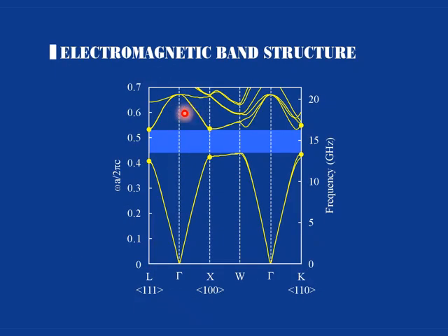So, okay, this figure shows the obtained electromagnetic band structures. This yellow line shows the Maxwell equation answers. Okay, here there are many Maxwell equation answers, and of course at lower frequencies also. So in these areas the Maxwell equation has answers, so the electromagnetic wave is possible to transmit to the opposite side. However, you can see that in these regions there are no yellow lines, so the electromagnetic wave is impossible to transmit to the opposite side. So this means perfect photonic band gap formation.